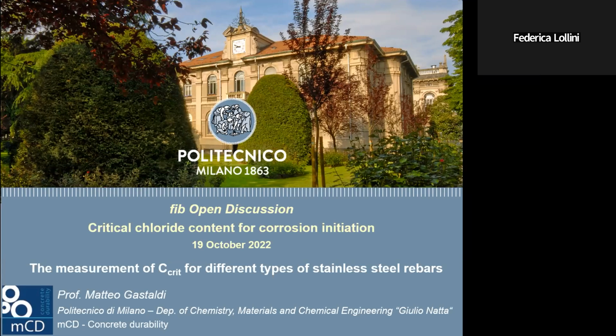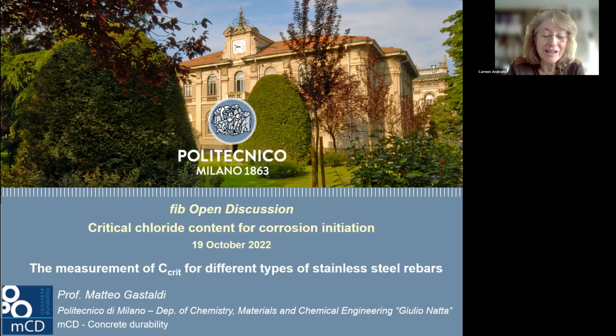Carmen? Yeah, well, thanks for the presentation. It's interesting to see all the types of stainless steel. My question is also about the mixing with the chlorides, because not only what you mentioned, but are you able to set the concrete with 5% of calcium chloride or sodium chloride? Because the calcium chloride accelerates until a certain proportion and after delays the setting. In that case, above 3 or 4%, the setting time is long.